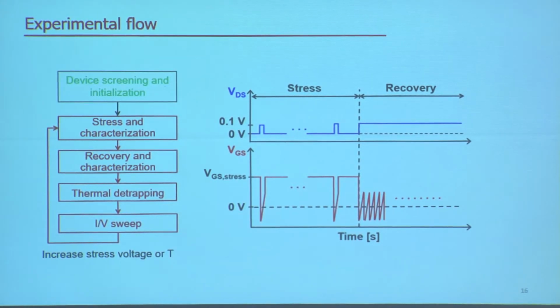Now, sometimes it takes a very, very long time for the device to recover, depending on the device time constant. So what we ended up doing is developing a thermal detrapping process to speed things up. We basically bake the device for a period of time, and that speeds up the process. At the end of the thermal detrapping, we do another complete IV sweep so that we know if the device is completely recovered or if any permanent degradation took place.